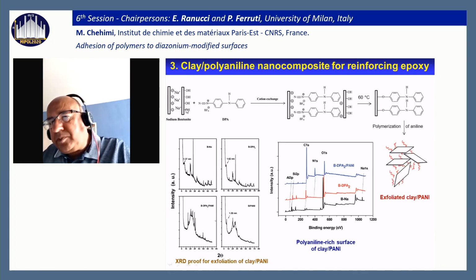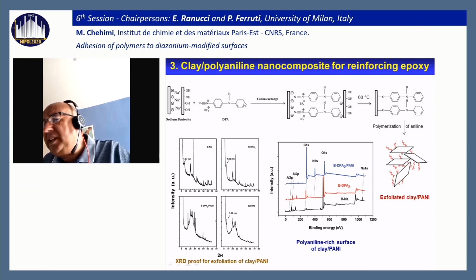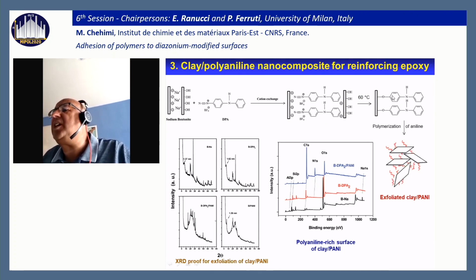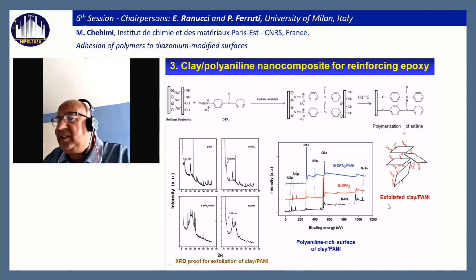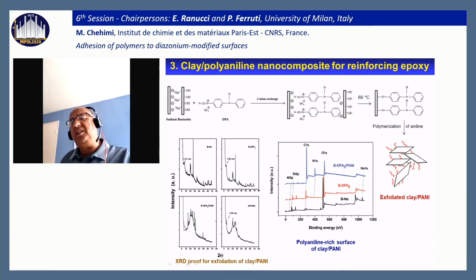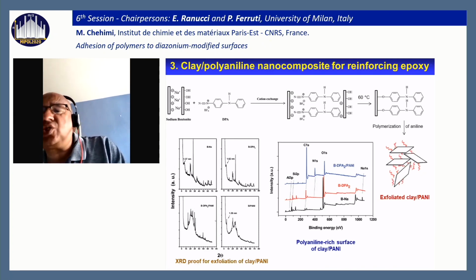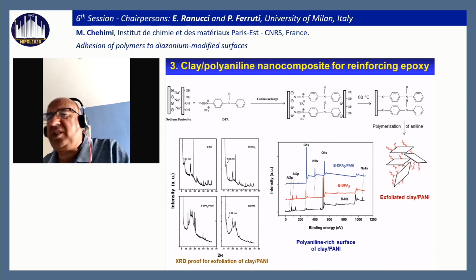We intercalated the clay layered silicate with this diazonium salt, which is used to start the oxidative polymerization of aniline. Intercalation was very quick. Curing at 60 degrees ensured the covalent bonding of the aryl group to the clay lamella, and in this way we obtained an exfoliated clay polyaniline nanocomposite. And here we can see that there is a loss of some important diffraction peaks from the clay, which shows that there is exfoliation or high intercalation of the clay with polyaniline.